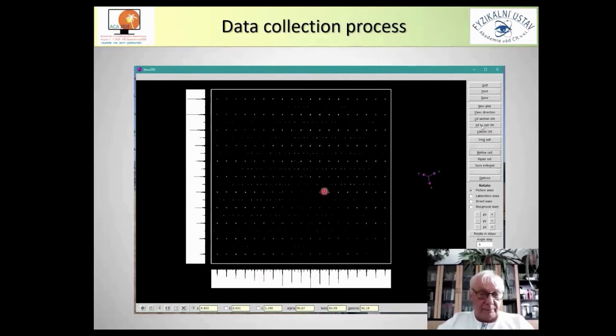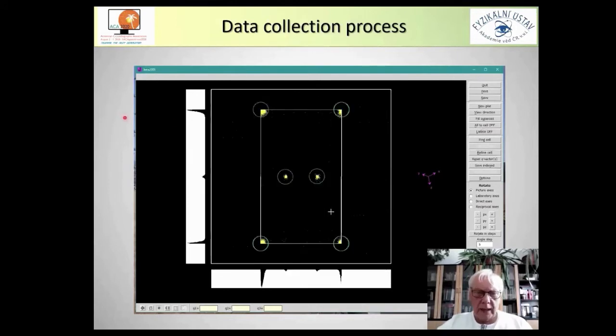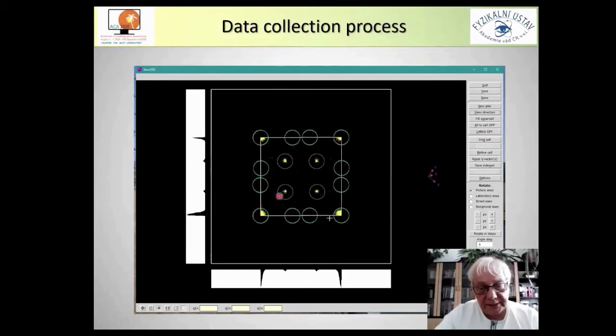First step is to find the basic cell. The basic cell we can find interactively, or we can ask the program to make it automatically. Then if we have the basic cell, we can continue this process, and we can project all diffraction spots, including satellites, into the basic cell. Then we have some additional information about the satellite spots, and from this we can localize modulation vectors. For this case, in fact, we have more than one modulation vector. From this projection, we can see that we really need two modulation vectors to describe all satellite spots. These so-called combined satellites are not present in this case, but they are probably too weak to be detected in the fast hunting procedure.